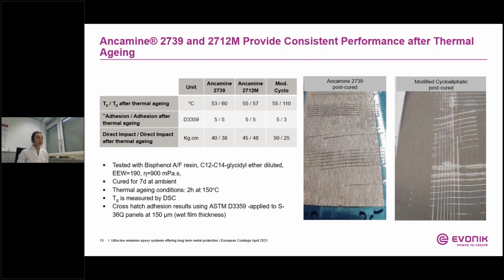This suggests that plasticizer migrates out from the coating during service life, with the consequent danger of stress accumulation and loss of adhesion. Same for direct impact. We observed a dramatic decrease for cycloaliphatics here as well. In comparison, 2712M and 2739 based coatings show no performance changes after post-cure. A panel used for the crosshatch test after post-cure you can see on the right side of the picture as an example.